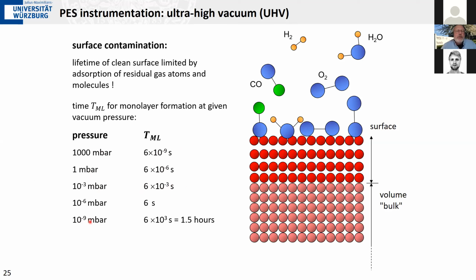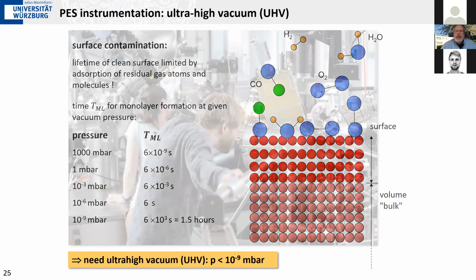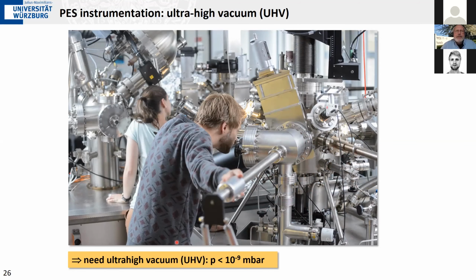You really have to go down to very, very low pressures of the order of 10⁻⁹, better even 10⁻¹⁰ or 10⁻¹¹ millibars, to get lifetimes which allow you to do a meaningful experiment. For example, in this simple estimate, at 10⁻⁹ millibar we have a lifetime of 1 or 2 hours. That's a typical lifetime, and very often, depending on the chemical reactivity of your surface, you still have to be quick to do these experiments before oxygen atoms, for example, change your surface. Okay, that's why we need ultra-high vacuum, and that's why you always see this huge amount of stainless steel in our laboratories, because we have to do everything under these conditions.